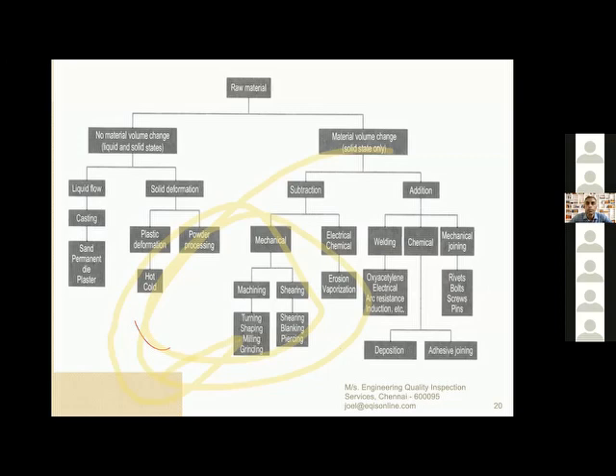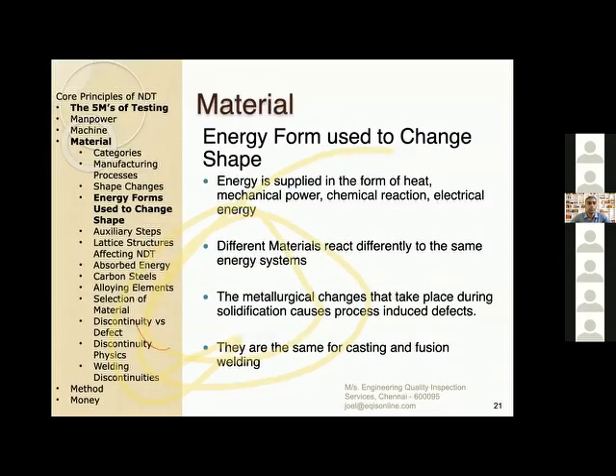Usual defects with casting are, let's say, porosity. A porosity is a gas, so it's going to have smooth edges. But whereas if I'm dealing with a volume change, then there are going to be cracks, which means that the crack is going to be more susceptible to failure than a porosity. So I will explain that in the forthcoming slides.